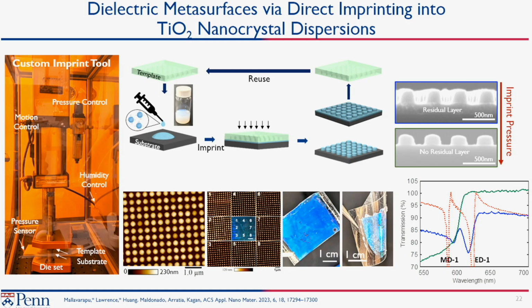All right, so we first started by building home-built instrumentation. One thing we had done many years ago, which I didn't talk about, was that when we first developed the gold and the ligand exchange process, we also developed an imprint process where we could directly imprint into the colloidal dispersion. No resist involved, no traditional lithography, and that's possible. And so we went back and did this now with dielectric materials, with titania nanocrystal dispersions. We chose titania because it has a large dielectric constant. We can imprint into the dispersion, and then depending upon the pressure, we can either leave behind patterned structures that have a little bit of a residual layer underneath, or if you press hard enough, you can leave no residual layer underneath the structures.